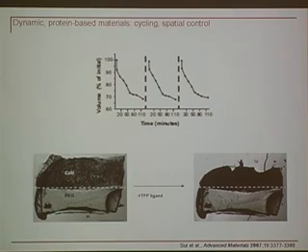This collapse in volume can be cycled. So what you're looking at here are multiple cycles of exposure to trifluoperazine ligand. And so the material gets back to its initial volume and then can collapse again. And then we can spatially control this as well. So if we create a polyethylene glycol hydrogel and then create a Calmodulin-based hydrogel adjacent to it, but sort of in the same network, if we add the trifluoperazine ligand, you can see that the Calmodulin side collapses and the PEG side remains intact. So it's possible then to sort of spatially control things as a bioactuator.